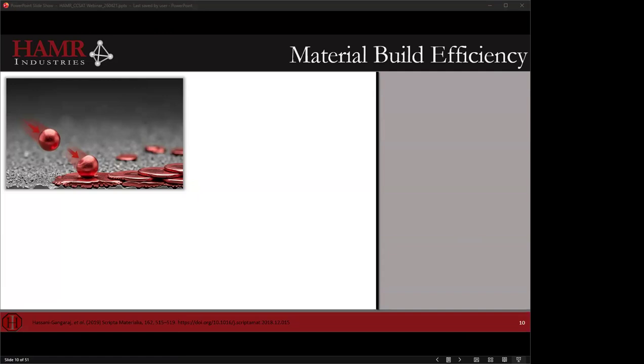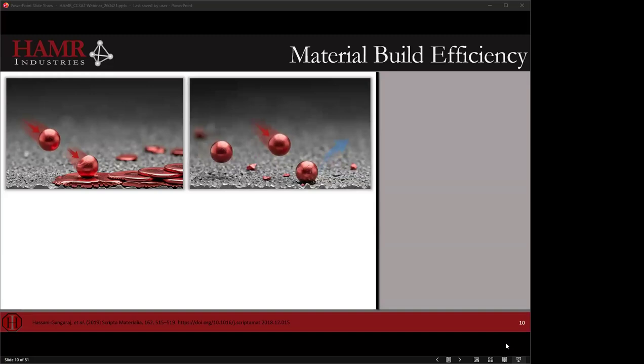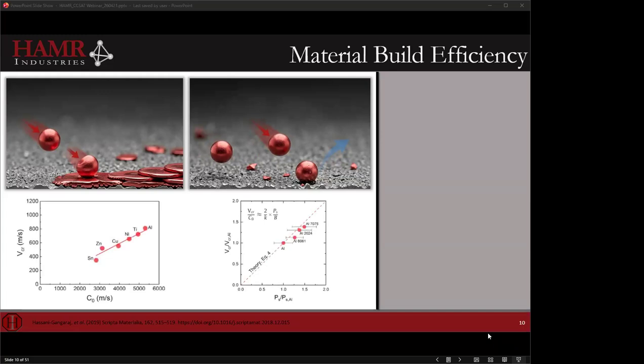So there's a fun little AI image that approximates the cold spray splat phenomenon. As the particle comes in, impacts the surface, splats, and deforms, we make our part. If our material is too hard, too high strength, too brittle, it can come in and break, shatter, or it can come in and rebound. And that leads to a low deposition efficiency. In the worst case, we just get no buildup. If most of our material gets bounced off or breaks, that means it's a very expensive process. Unlike powder bed fusion and some of the other modalities, we're not able to reuse our powder at this stage. So whatever we lose is lost forever.